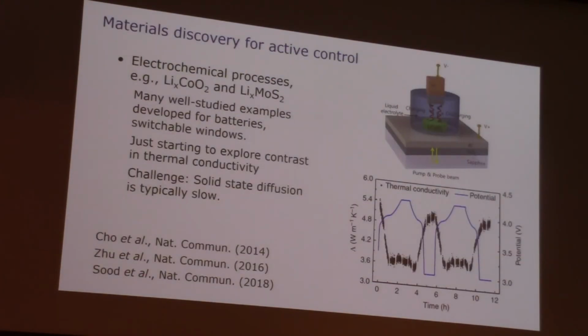Okay, active control. So something that we can switch, and I'll finish with this. This is one example that goes back some years. I guess that's this paper, 2014. Other groups have done this too. This is one of our papers too. This is from Stanford, where with electrochemical systems, you could intercalate lithium, take lithium out, you basically charge and discharge a battery, and its thermal conductivity changes. So here's the thermal conductivity of a lithium cobalt oxide as a typical cathode material in a lithium ion system, where the thermal conductivity drops from 5.4 to 3.6 as you charge and discharge the battery.